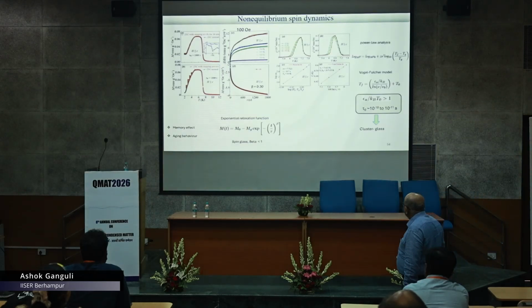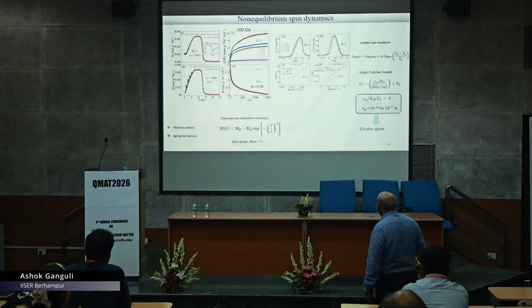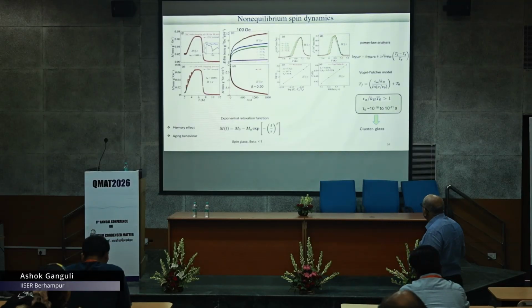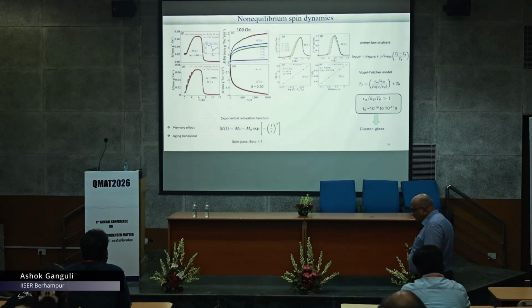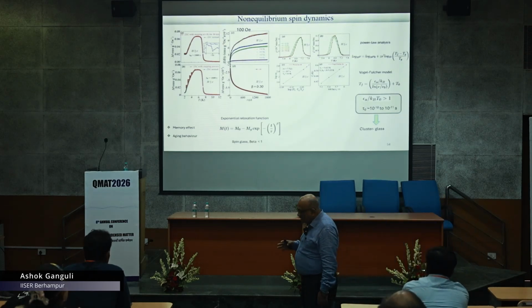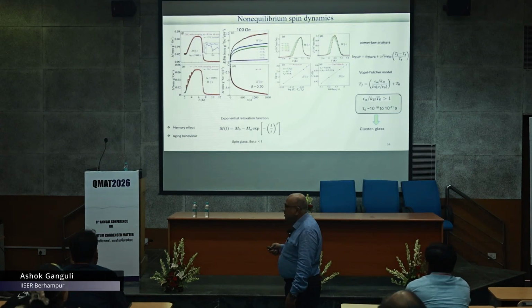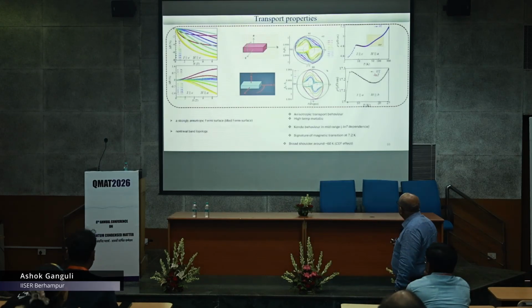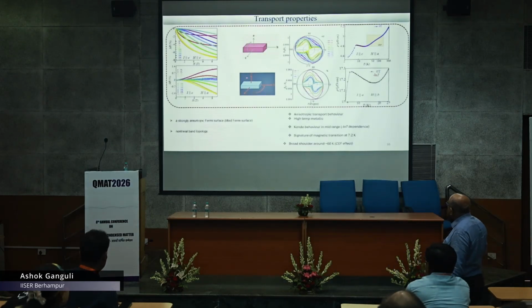These numbers below 0.3 suggest that it is a kind of spin glass, and doing this analysis, it comes to 10 to the power minus 10 to 10 to the power minus 11, which gives you an idea that this may be more like a cluster glass behavior. And here also we did the transport properties.